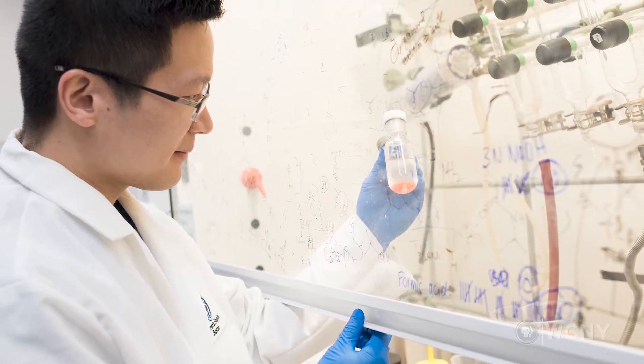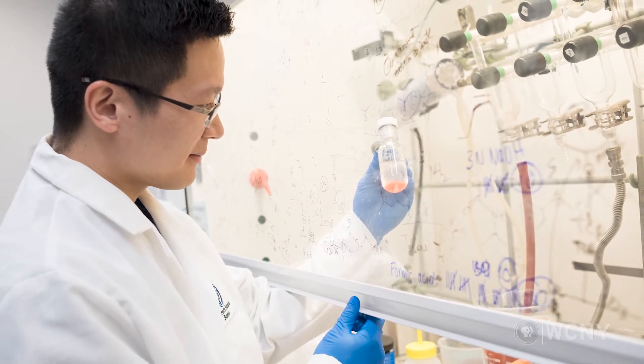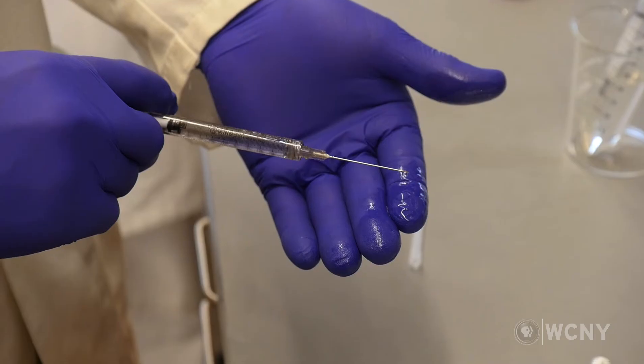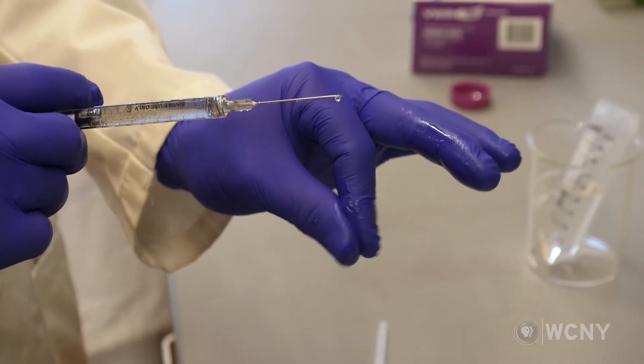The student who made this material is Jason Sun, a polymer chemist who has been working in the lab ever since he was a master's student. There are elements of the molecule involved in bringing in water and elements that involve binding to the tissue. If you mix them up, the molecule doesn't work at all. You need the anchoring domain to be sufficiently large, the lubricating domain to be sufficiently large, and they need to be on opposite ends of the molecule to work correctly. Jason's work was really instrumental in demonstrating how the architecture of this molecule needs to be exactly right for it to work.